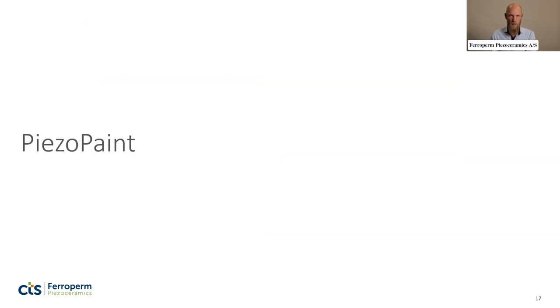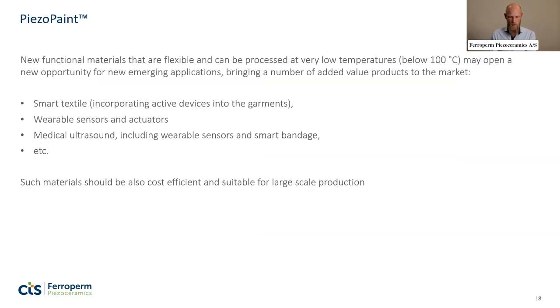Okay, so that was thick film, and then I'll spend the next 10-15 minutes talking about the PiezoPaint. So coming back to the drivers for developing this kind of technology, the ceramic technology, of course, has the limitations that you need to fire the ceramic at very high temperatures, up to, for thick film, 800 to 900 degrees C. For bulk it's even higher, but of course that limits the application space in terms of what kind of substrates can be used if you want to deposit a film on something, and it has to go through this processing step of high temperature firing. So trying to integrate a film into polymers or textiles or even PCBs, that's going to be a challenge if you want to make a ceramic that needs firing.